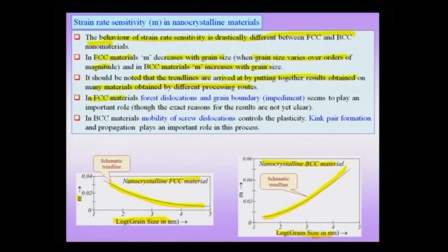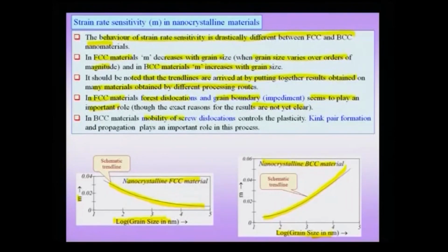In FCC materials, so far our understanding goes that forest dislocations, that means a single dislocation cutting through a forest of other dislocations, and grain boundary impediment seem to play an important role, and the exact reasons for this strain rate sensitivity are not yet clear. So, we will not discuss that aspect more, but this forest dislocation hardening mechanism and also the grain boundary impediment mechanism seem to play an important role in FCC materials. In BCC materials, on the other hand, mobility of screw dislocations seems to control the whole plasticity.